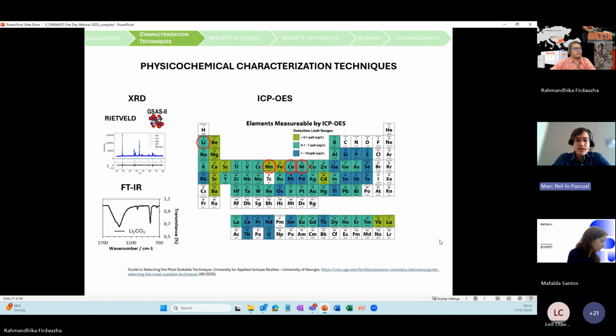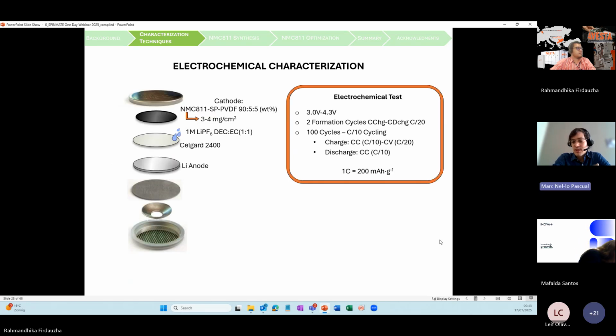Rahmandhika, can you go to the next slide, please? Okay, so we did different electrochemical tests. There is a wide range of techniques that you can use to characterize, but in this presentation, I will only be showing some results from cycling tests. This protocol consisted of a voltage range between 3 to 4.3 volts, 2 formation cycles at C/20, and then 100 cycles at C/10, assuming a capacity of 200 milliampere hours per gram, which is the value expected for a good NMC material for a commercial sample.